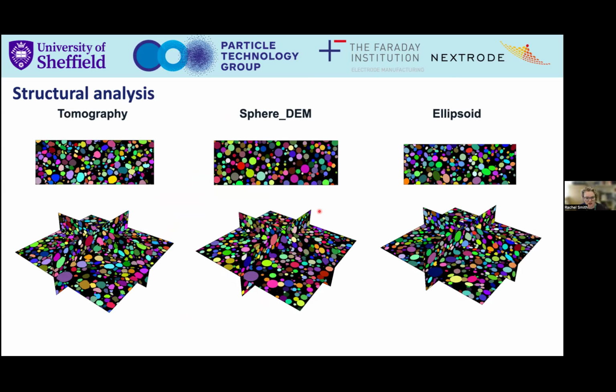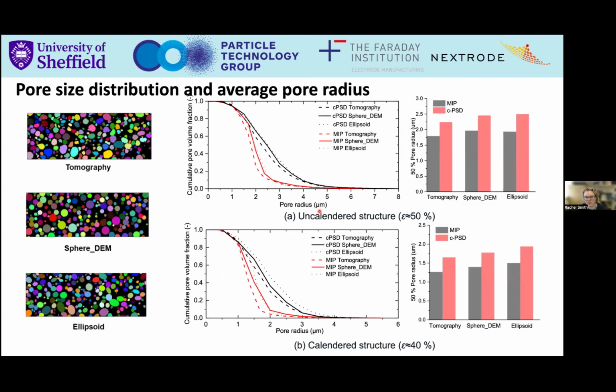So we took that tomography scans and we basically said, okay, let's say they're all spheres, and then let's say they're all ellipsoids instead. And the ellipsoid obviously has that degree of freedom that you can change the aspect ratio. So we replaced each of the particles with ellipsoids and DEM, and then we ran our DEM again.